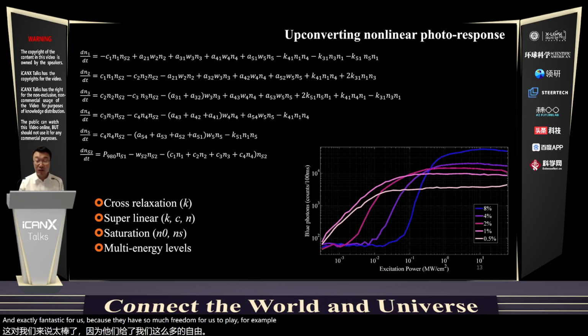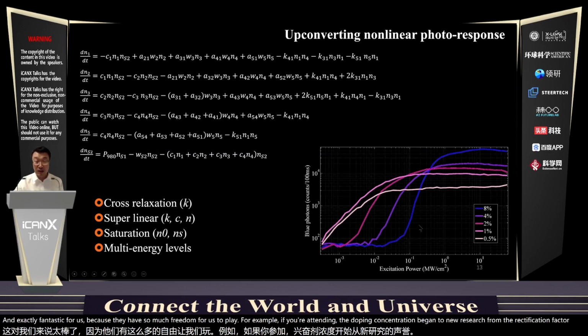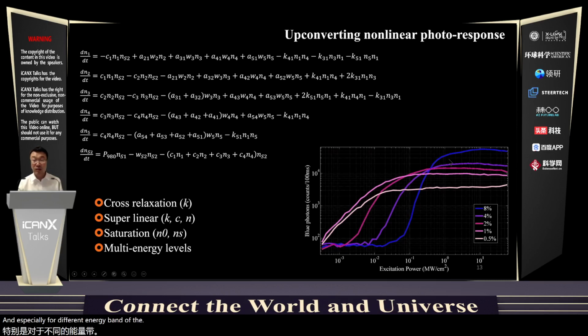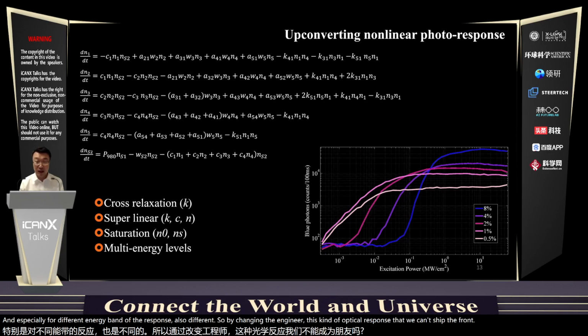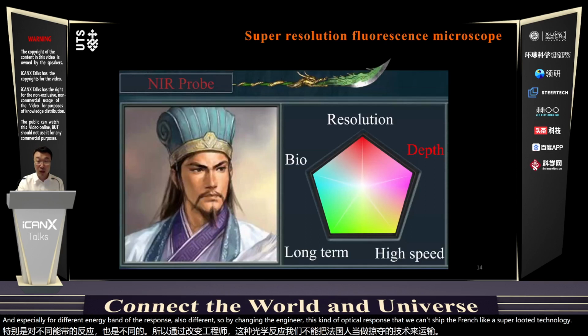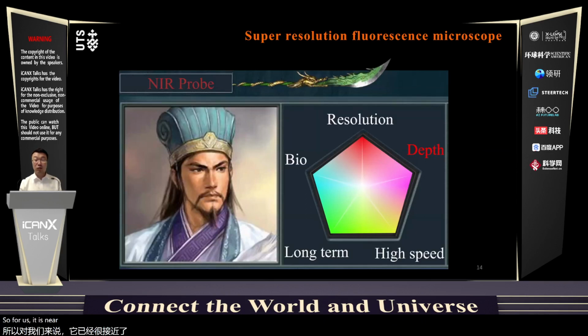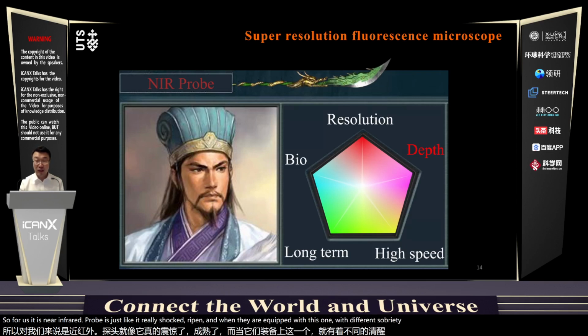For example, if you change the doping concentration, we can tune it with the cross-relaxation effect. We can make it superlinear and also saturating. And especially for different energy bands, the response is also different. So by engineering this kind of optical response, we can achieve different super-resolution technologies. For us, this near infrared probe is like a really sharp weapon, and when we equip it with different super-resolution technologies, we can substantially increase the working depth.